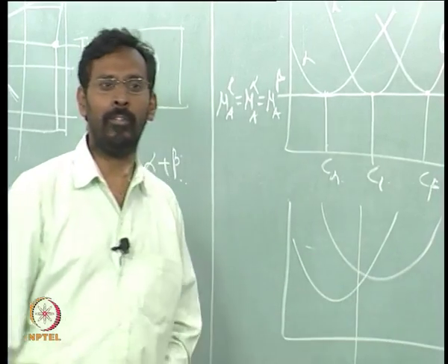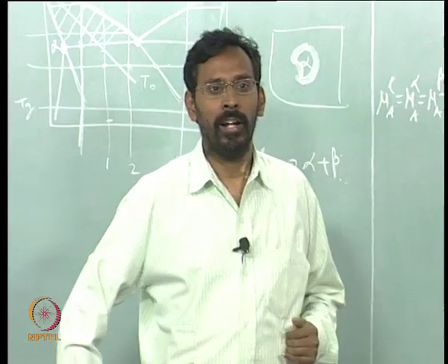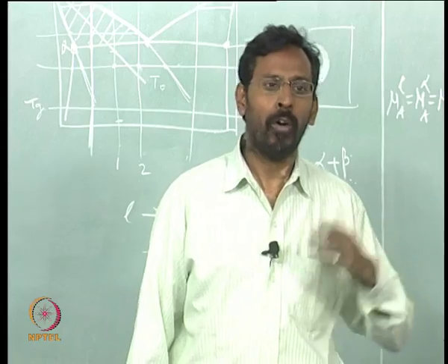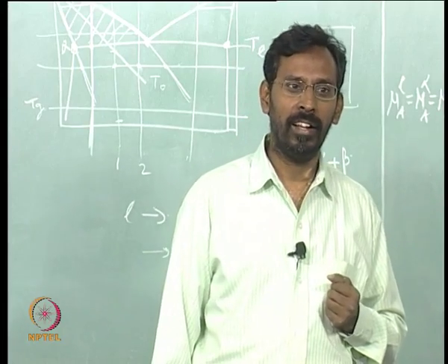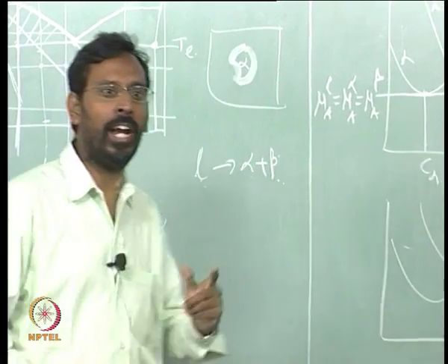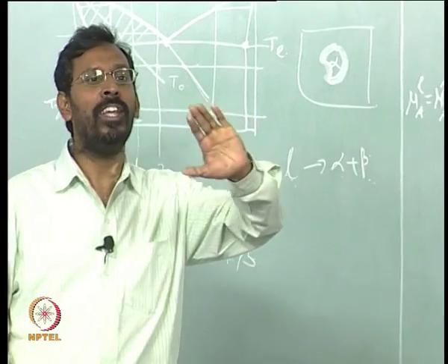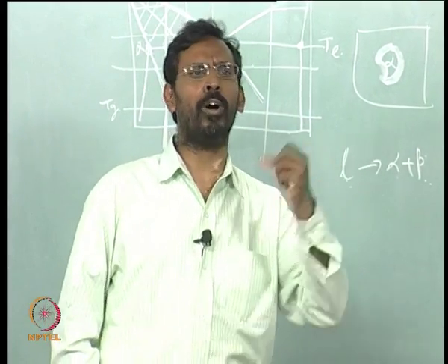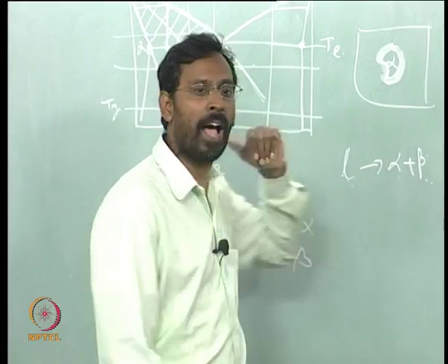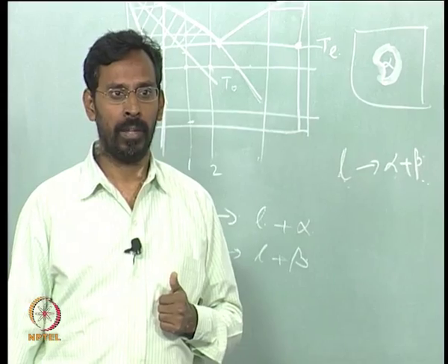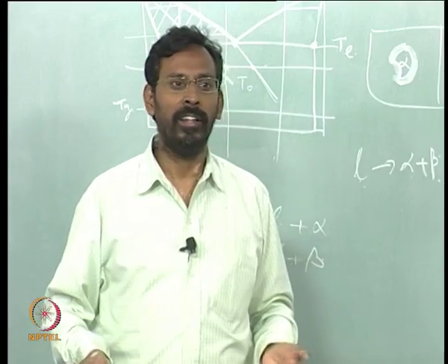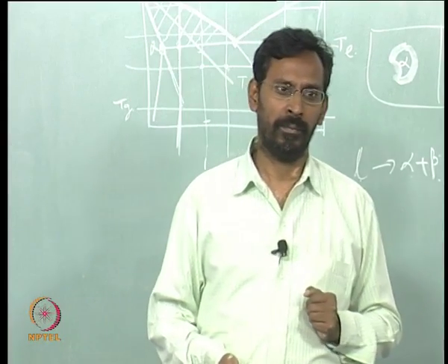Just because there is a driving force, will it form or not is decided by the structure of that particular phase, how complicated or how easy it is, whether it is able to nucleate or not. If it can nucleate, that means the diffusion is able to take place, even if it is localized diffusion, and if localized diffusion can happen, then local equilibrium has to be established. If local diffusion also is difficult, that means short range diffusion is also difficult, then there is no chance of even local equilibrium.